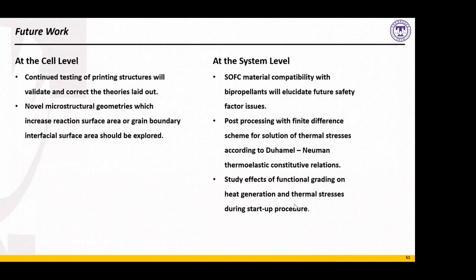Future work at the cell level, again, continued testing of printing structures will validate and correct the theories that we have laid out. And novel microstructural geometries that increase the reaction surface area or grain boundary interfacial surface area should be explored and can be explored with very little modification to our theory. So this could involve columnar grains that have a very high grain boundary conductivity in the case of, like, an LSM cathode. Our stochastic geometric relations would apply to those as well. Someone would only need to substitute the shape factors for those grains and their respective percolation probabilities.